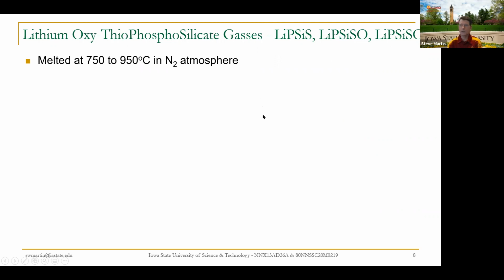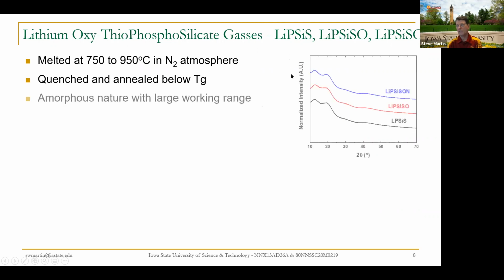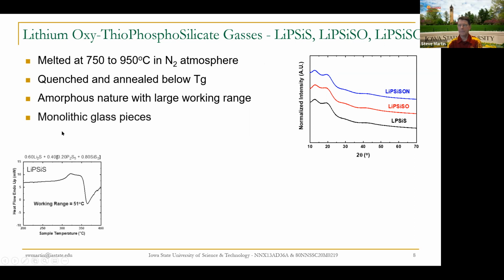Remember back to the original story, I said that the glasses can dissolve many components. Well, now you can vary the composition. The sulfide glasses were among the first to show high conductivity, but the sulfide, pure sulfur, is actually reactive. We can add the oxygen to oxidize the glass and stabilize it a little bit. We can add nitrogen to even stabilize the glass even further. And again, it's just this compositional optimization.